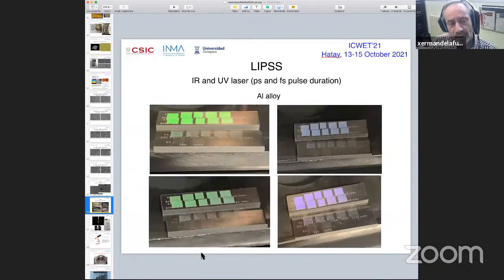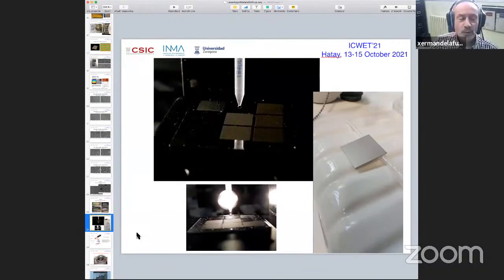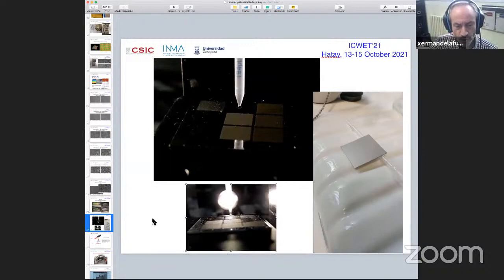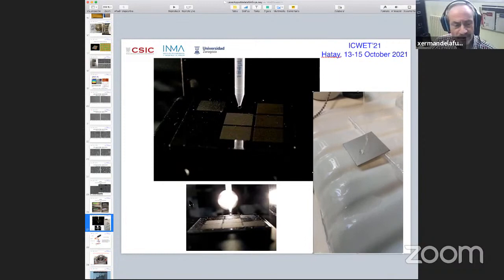And what you can get when they're on the order of visible light is, as you change the illumination and the observer's angle, you can see this is the same aluminum alloy plate. Depending on the angle, you can see all these nice colors, very intense. So this is a very nice diffraction grating. And besides that, you not only change the optical properties, but you can change other properties like the wetting properties, for example, as you see here. So this is one of those surfaces. You can see also here in slow motion how it rebounds, and you can see underwater what the effect is. This is all aluminum alloy, in fact. So this is very interesting.